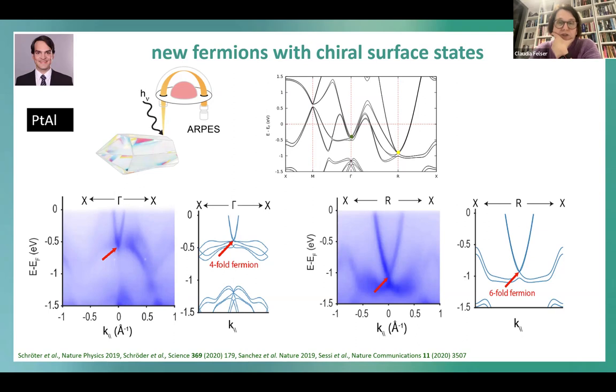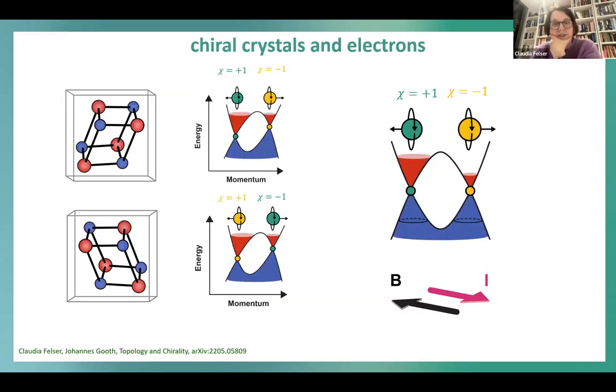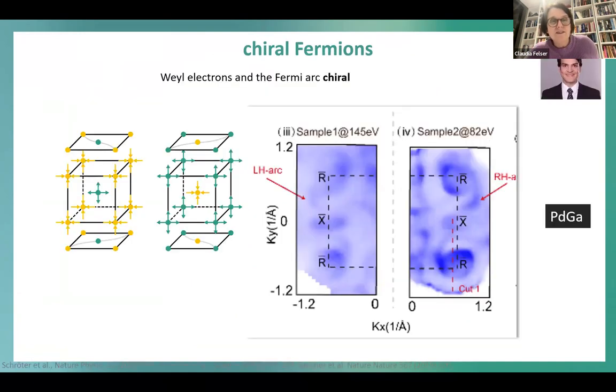And the next slide shows that my chiral crystals, with two different chiralities, are more or less like a moment of my Weyl semimetal, you know? In the Weyl semimetal, I'm dynamic, I can switch the chirality, okay? Here, I can learn a lot since I have both handedness in two different crystals, which is also an advantage, you know? And the next slide shows then the Fermi surface states,